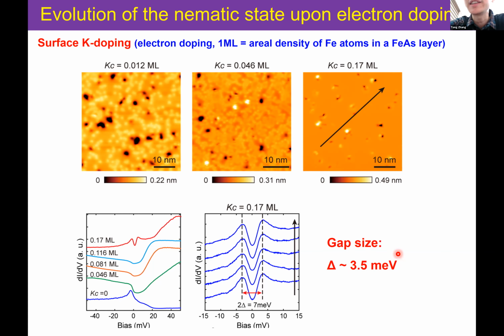It's much larger than the gap on the undoped surface, which is about 0.5 meV. So we think it's due to the electron doping. Actually, at this doping level, it is close to the optimal doping.